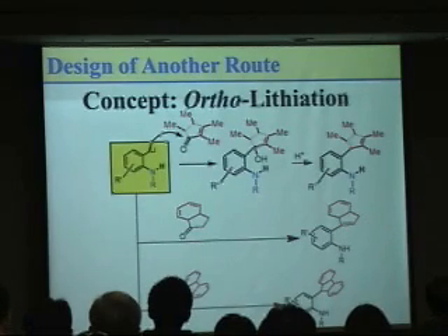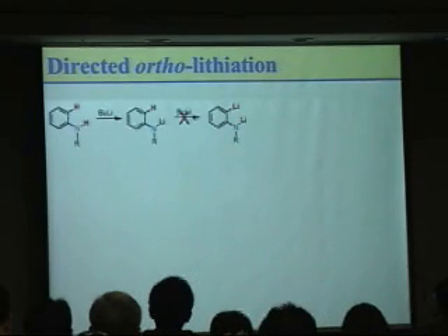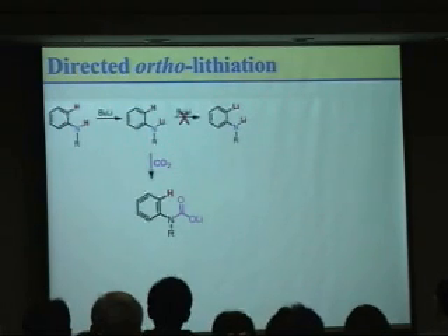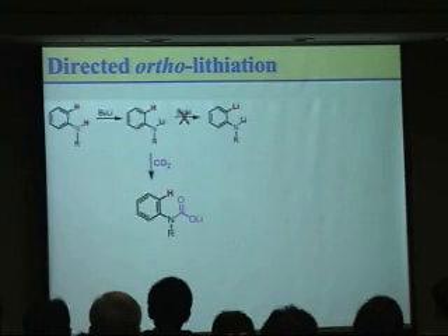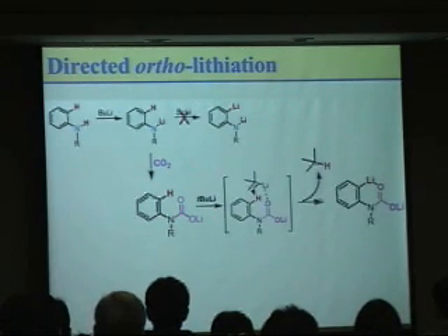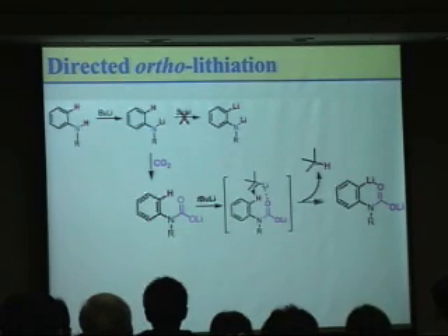So I have focused on generation of this lithium compound. When I added one equivalent of this lithium reagent to this very cheap starting material, lithiation occurred on the amine proton because this proton is more acidic. And nothing else happened. Because I have carbon dioxide in my lab, I thought addition of carbon dioxide would convert this lithium amide to lithium carbamate, and this lithium carbamate acts as the directing group in ortho-lithiation reactions, liberating the targeted ortho-lithiated compound.